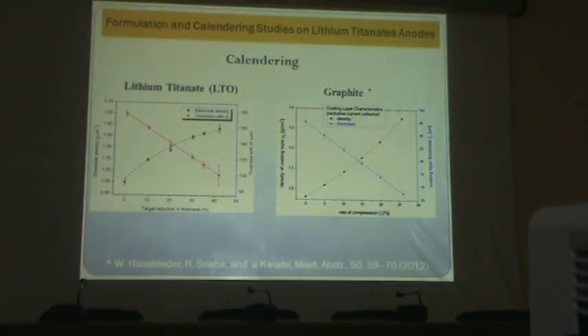So now once we have formulated the thickness and the formulation, we went for calendering, which is essentially nothing but reduction of thickness to pack more active material. So this is a comparison of LTO with graphite. You can see more or less at 20% thickness reduction, the density is more or less the same. So this slide doesn't mean much, but I just wanted to show you. More or less we are in a similar trend of calendering. It's basically the electrode density, how much active material is packed in the electrode, and whatever thickness reduction you are going for. So it's more or less the same for LTO and graphite.